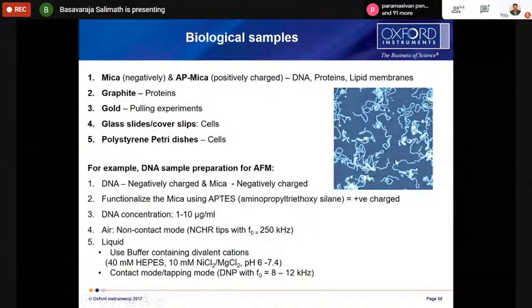For example, if you want to do DNA imaging, as you know, DNA is negatively charged. For DNA, mica is a good substrate, but mica's surface is also negatively charged actually. So if you put the DNA on this mica, as both are negatively charged, the adhesion between the DNA and mica will not be good. So when you are scanning, these DNAs may move. So we need to fix these DNAs on the mica. Then only may we get good imaging.